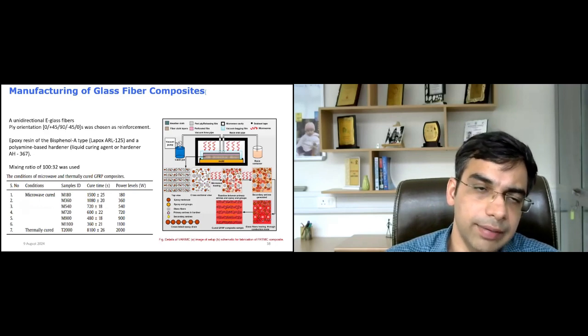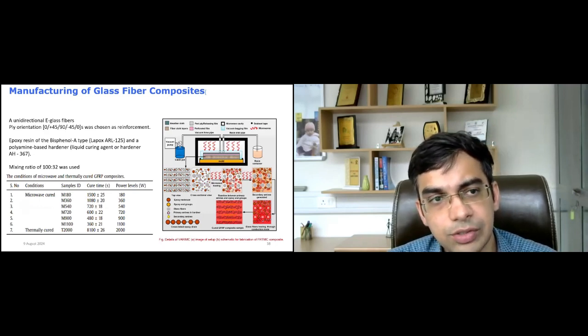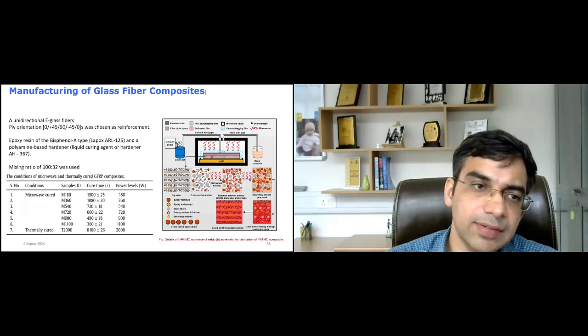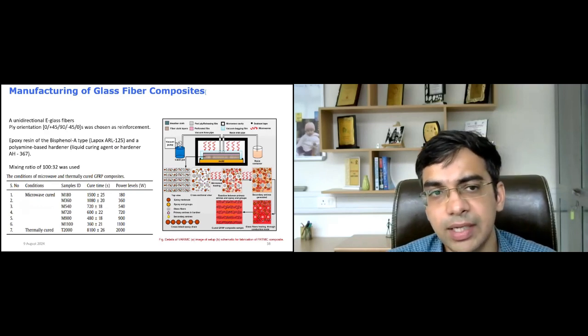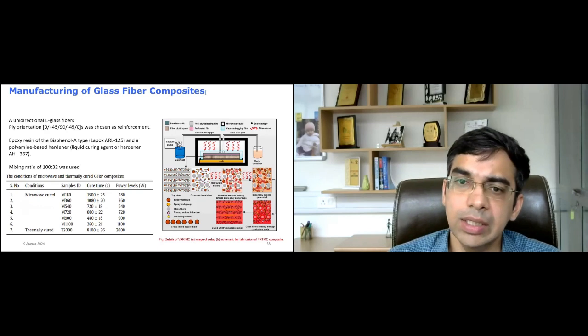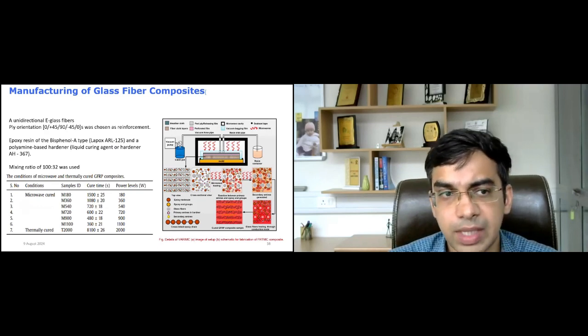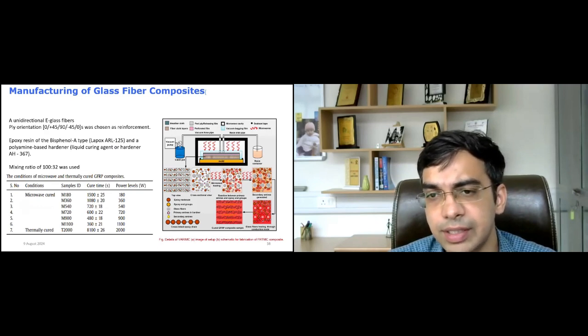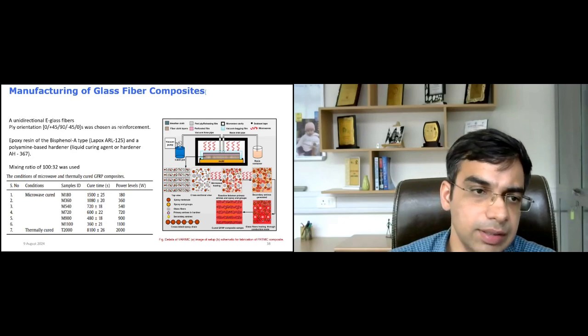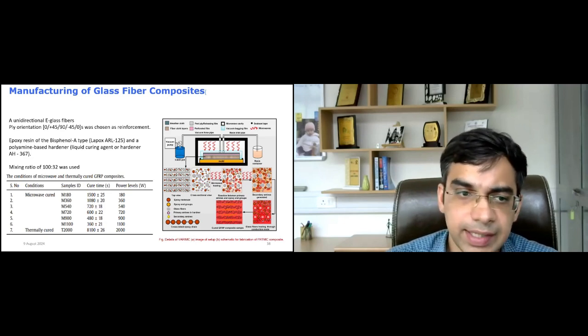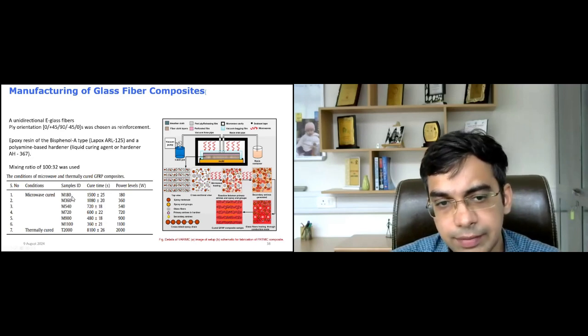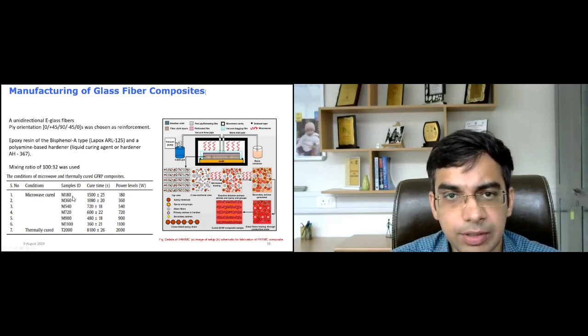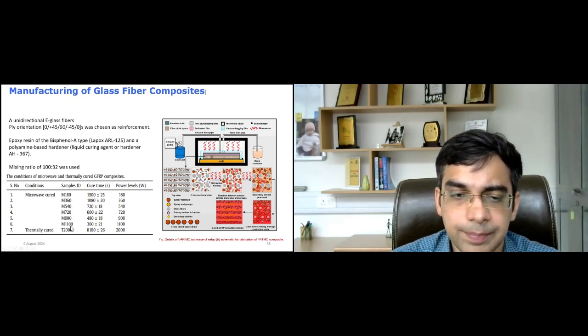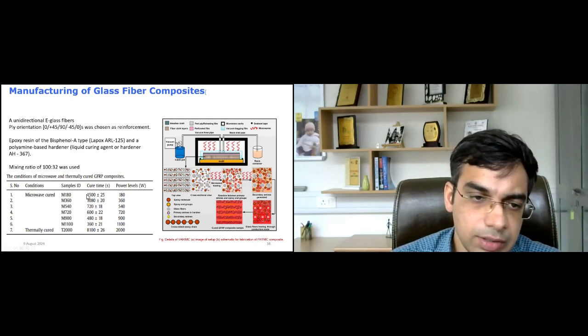In this regard, we have demonstrated the use of microwave energy to develop composites utilizing unidirectional E-glass fiber in a ply orientation as mentioned here. It was a symmetric ply orientation with almost 10 plies as reinforcement. The epoxy that we have chosen was bisphenol A with polyamine hardener, and it was mixed in the ratio of 100 to 32 as specified by the manufacturer of the epoxy. In microwave, we have performed the manufacturing or curing here, because this is a thermoset, at different power levels starting 180 watt, 360, 540, 720, 900 and 1100. At these various power levels, we could also get the cure cycle time, which was of course measured in seconds.